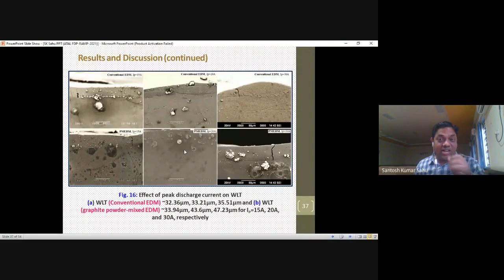Again, the white layer thickness is an obstruction, because when the white layer forms, the layer is uneven. The layer is not uniform, because we have to know about the built-up edge: the white layer is built unevenly, so the Ra value will increase if the roughness peak to valley is there. Within the gap between peak and valley, some debris is present in the blocked area. That is not possible to remove by our flushing pressure. It should be removed, but we have to minimize that to some extent.